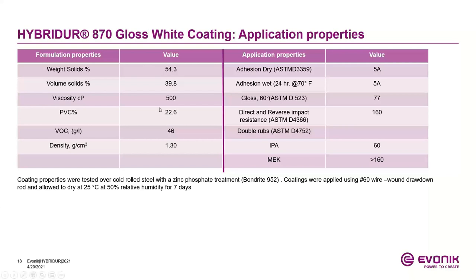And on the application properties, we measured both wet and dry adhesion. They provide an outstanding rating of 5A, which is the highest you can get using the test, with a gloss of about 77. Again, they provide outstanding impact resistance. This formulation has direct and reverse impact resistance of 160 or higher. And outstanding MEK double rub resistance, greater than 160. And with the alcohol, just a little bit less, it still gives you about 60 IPA double rubs.